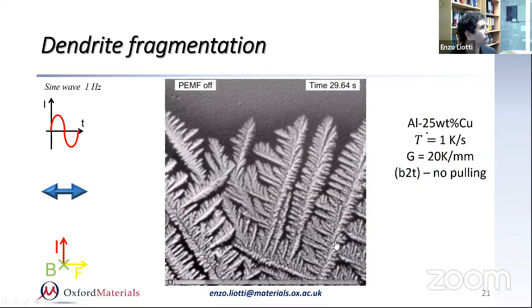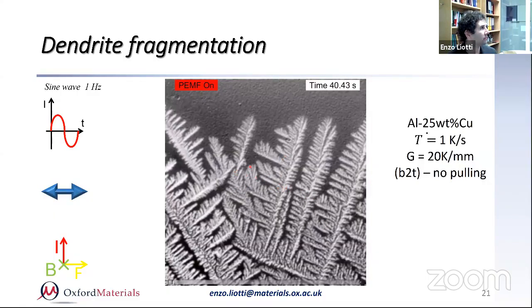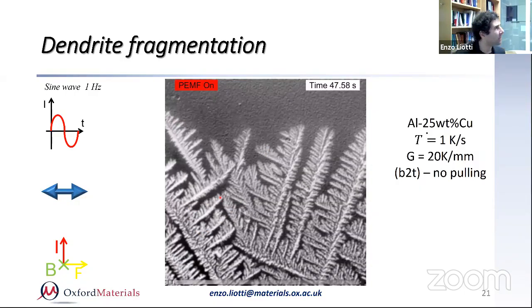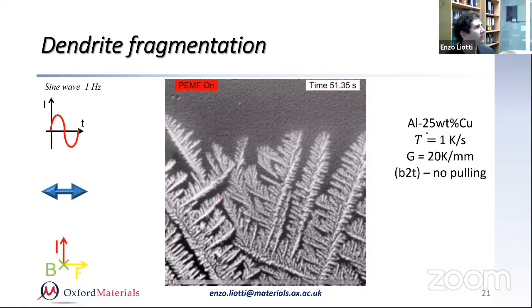It's about 32 seconds. This was grown from an aluminum copper alloy, and you can see, if you look carefully, we are stirring the liquid. Clearly, you don't see the liquid stirring very well because you can't really see the flow, but you see the effect. So you see that there are a lot of secondary arms that are breaking. And of course, in this case, because it's static, they are basically stuck in the mushy zone. But equally, they are breaking.